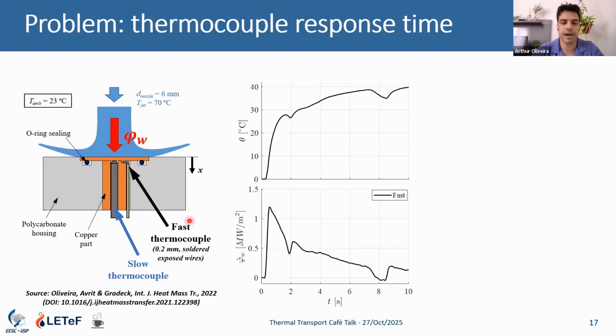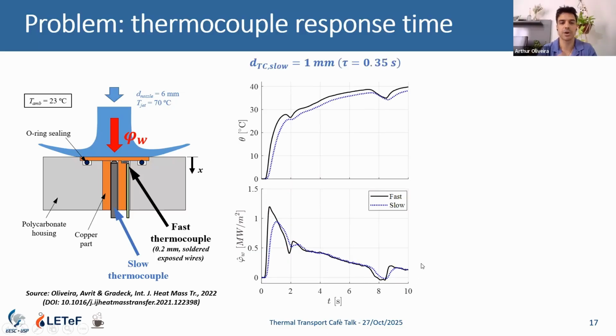When you do this, you have the fast thermocouple here, the thermal response, and the estimated heat flux with this fast thermocouple. When I use the slow thermocouple, for example a 1 millimeter thermocouple, it's lower, we can see the thermal response is dampened, and the heat flux estimate is a little affected.